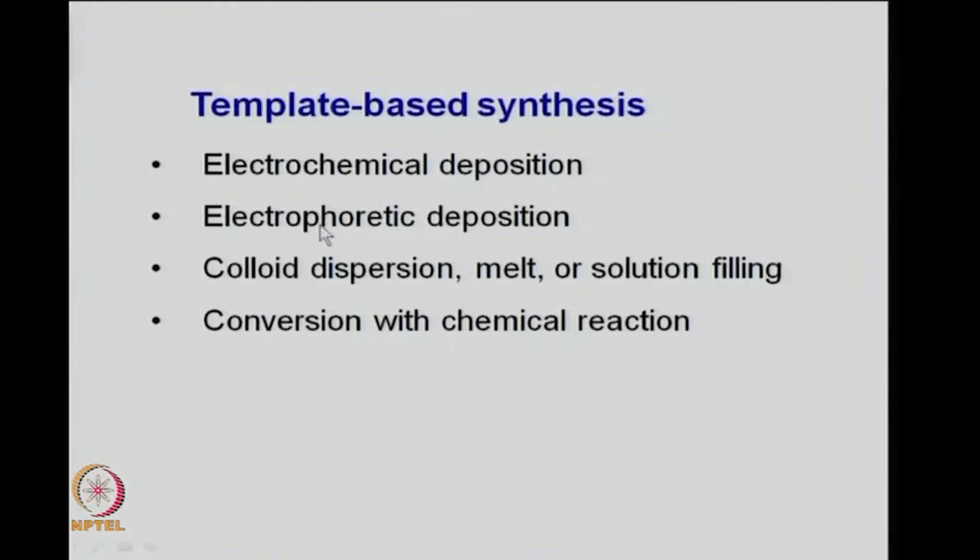One important thing is that in electrochemical deposition, you need to work with conducting specimens, that means metals, alloys, etc., whereas electrophoretic deposition you can do with materials which need not be highly conducting.